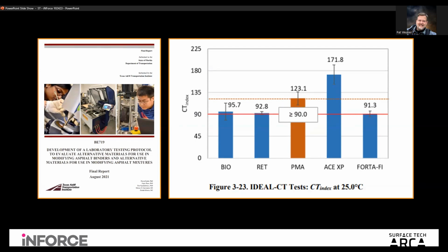And so this is just a snapshot of one of numerous pages in this report. But when you take the polymerized mix, one that has 3% SBS, into the neat binder, and then we just add 1 dose of our ACE XP, you can see the huge impact on crack resistance. This is a CT index test, and we go from 123 to 172, outperforming anything that they tried in their repertoire. And we know that a 3% SBS binder places so much easier than a 6 or 7%. And that's what they're trying to compare against in this report.